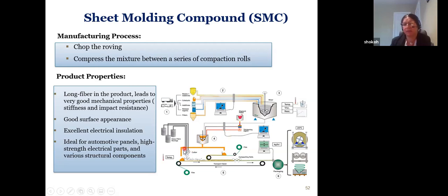Now you have a paste, the main material coming through, but you have to put films underneath and then put this paste on. This is a continuous process. You add chopped fiberglass on top. The good thing about this process is you can have long fiber in the composite, and then it goes through compression rolls. Then you let it cure, remove the films, and bring it to ambient temperature. This has the advantage of allowing long fiber in the product, which gives high mechanical properties. In a lot of places I need high impact and high stiffness, and this gives good surface appearance and excellent electrical insulation. So basically it's good for panels, electrical parts, and other structural components that need a high modulus.